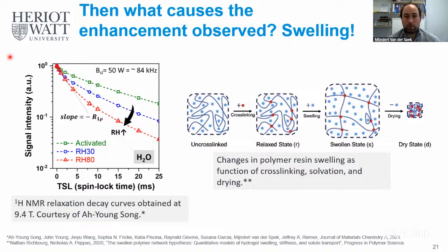So, had we been polymer chemists, then we would have probably understood quite quickly that resins swell. CO2 can be a solvent for resins, water can be a solvent for resins, but both make a material swell. And you also have to remember that these materials are amorphous. So if the partial pressure of an adsorbate is very low, what you will have is a material that looks like this here on the very right. So it's kind of shrunk and shriveled into a very dense little bead with basically nothing in there. There's nothing in there to keep these pores open. And as you start to dose water, the water just pushes the pores open. So that means that it generates access to pores that were previously closed. And that is exactly what is happening with these polymer resins and why water enhances CO2 adsorption.